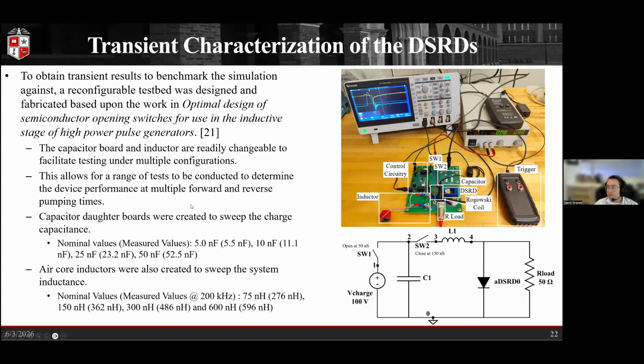And so one of the first things that we did on the modeling efforts was to consider some of the practical design considerations of the DSRD based purely on what was provided to us. So with that, the first thing we could extract from looking at the physical device was to estimate the active area to be equal to the anode contact size. We can see this is the device here under the microscope. We can see the anode contact here is about 1 millimeter wide, while the entire die is 2.43 millimeters wide. So with that, we ended up with an active area of 7.85 times 10 to the negative 3 centimeters squared.